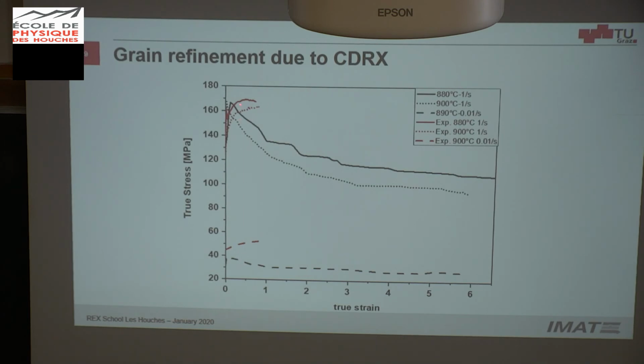So what I'm showing here are experiments of the flow curves of compression test, the same I showed before. Now they look a bit weird in this scale. And the torsion tests. So in the torsion test, the first thing you see is also an increment in the dislocation density, but we have a huge drop in the stresses. At very large strains, we also have a plateau.